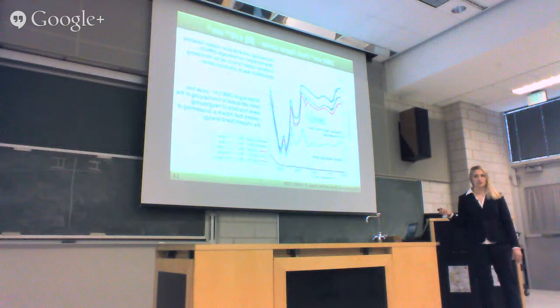So we take a baseline, we turn that into the absorption coefficient, and we multiply it by this 8 times 10 to the 17. So this works well for lightly doped samples, that's samples with very low boron concentrations. But as we increase, so I'm showing you here the ratio of boron to carbon in the plasma feed gas within the CVD reaction. As we increase that, we see that this works great. You can draw a baseline no problem for these lightly doped samples. However, as you get higher and higher boron concentration, you start to see that it's very difficult to draw a baseline here due to this broadening, and then eventually at the highest limit, you're above detection limits due to photoionization in the sample. So for very heavily doped samples, we need to look to a different part of the spectrum in order to figure out how much boron is actually in the sample.